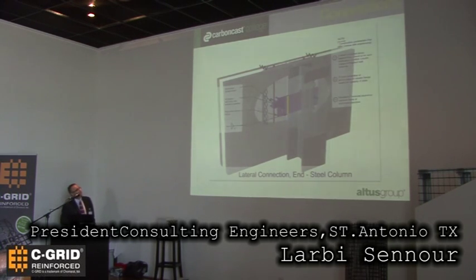You have to do it, very thin when you have a 5 centimeter wythe on both sides, and you have to put inserts to lift it. You have to reduce your insulation so you can get the insert in there. Or you need to put a gravity connection, you have to reduce. But in our practice, we never bridge the two wythes with solid concrete. The only thing that crosses the two is always the grid. Never steel, never anything else. And we have done thermal testing also to see the reduction, and the reduction is very, very small. And we have formulas to calculate that reduction also.